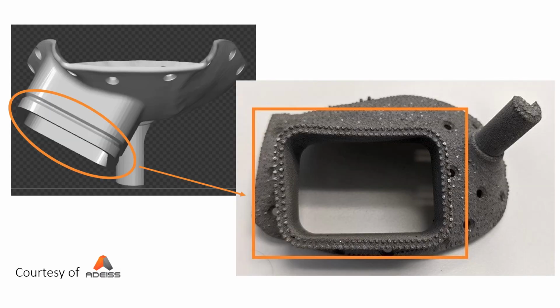So to make this real, let's have a look at this 80% of build failures or small failures that may be related to orientation or support. So this is an example from ADEISS. It's a medical device. The build orientation is as shown in this image here on the left. Up is the build direction, and we have a fairly organic shape, and then we have a prismatic shape. After it's been printed, the rectangular shape here has some distortion, and this turns out to be unacceptable. And the question is, this is a small failure, it's not catastrophic, but the question is, what was the cause of this distortion?